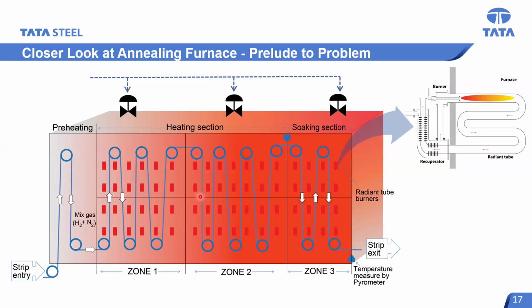So how do we control this? We have about 100 to 150 radiant tubes inside the furnace. These radiant tubes are grouped into different zones for the purpose of controlling the furnace temperature profile. By regulating the fuel flow into the radiant tubes in each zone, we can control the temperature in each furnace zone, which in turn will have its effect on the strip temperature.